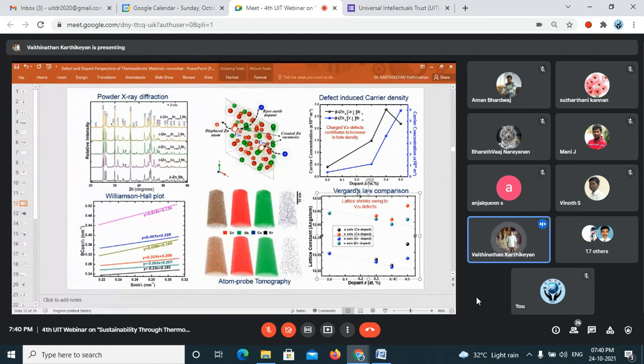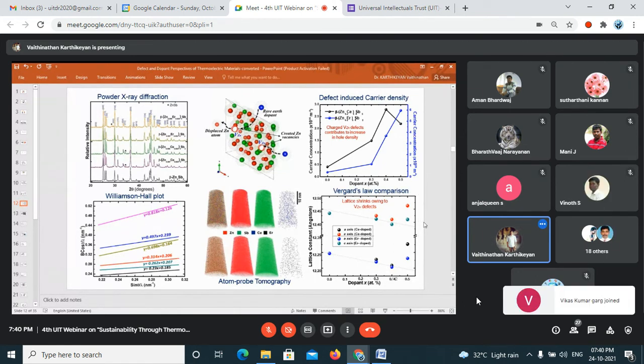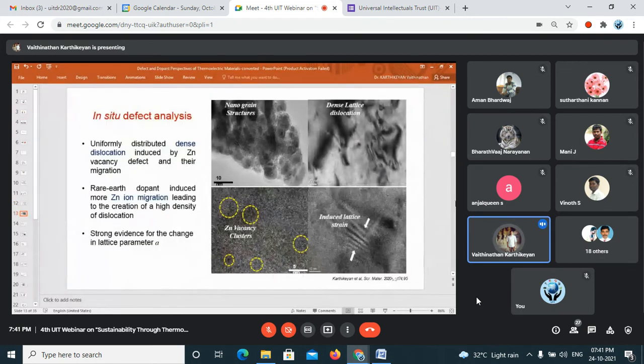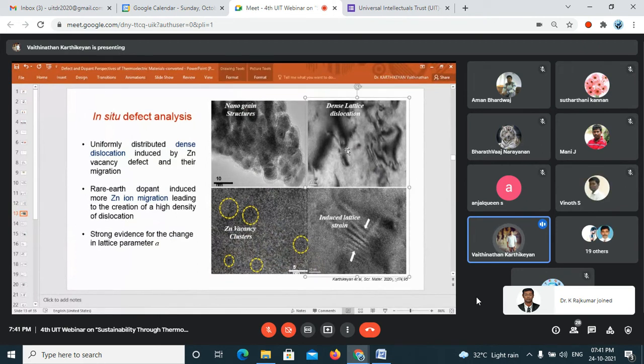And another case is here, what is present? It means that when you dope any element into a lattice structure, it creates defects, which can be observed through the lattice constant changes. Concentration. The lattice constants A and C duration starts to decrease, whereas for the highest concentration of 0.5 it starts to increase. It means that after that 0.5% it starts to accumulate into the lattice. So we can determine that 0.4 or 0.3 should be the ideal concentration. So yeah, we analyzed how the defects are formed in the material.